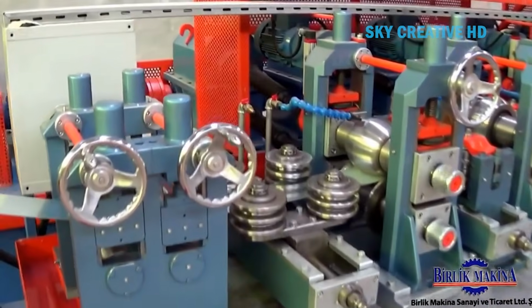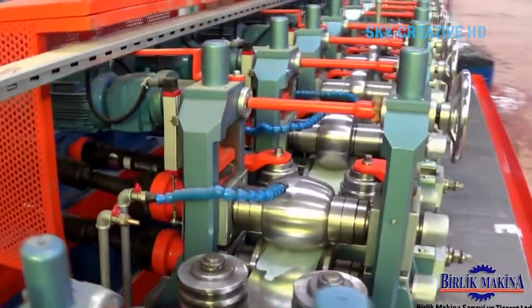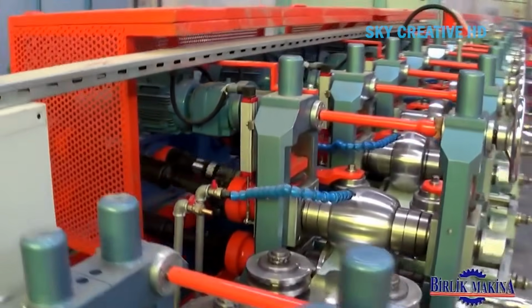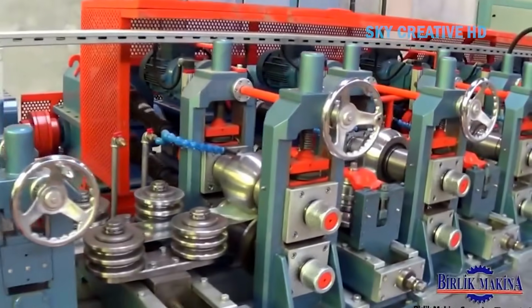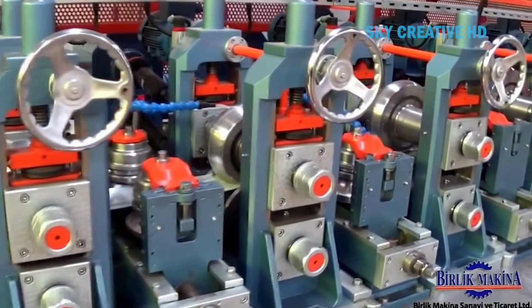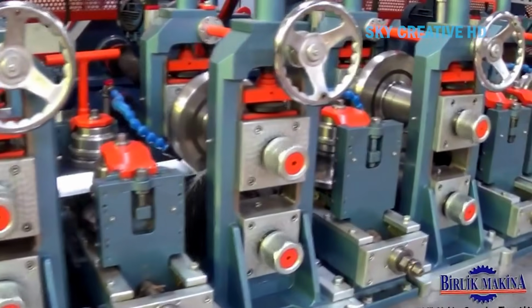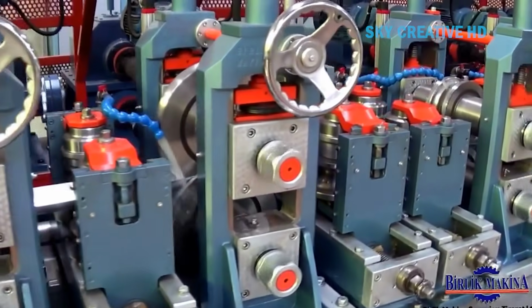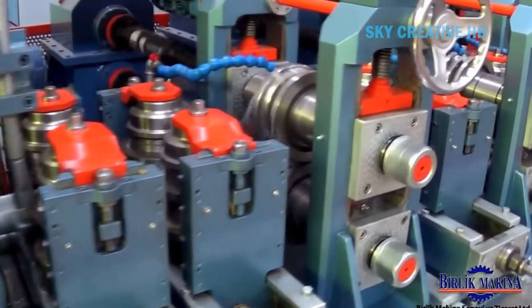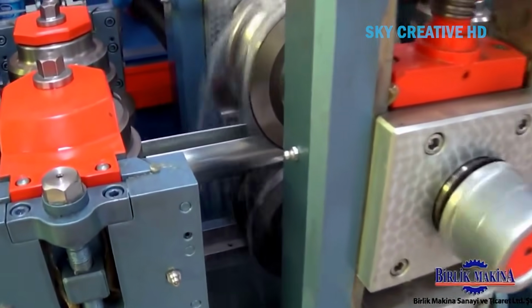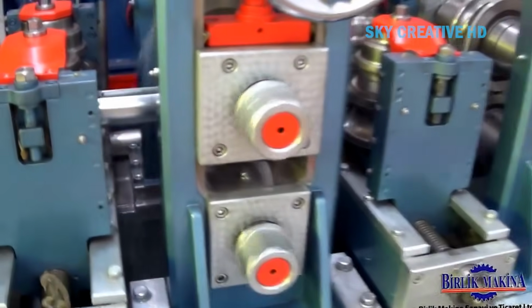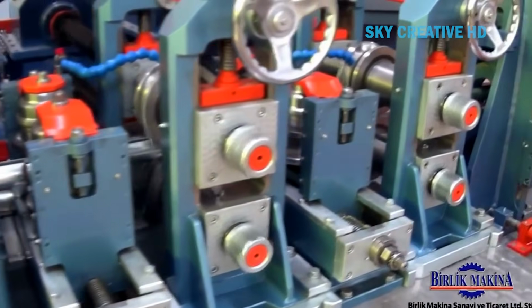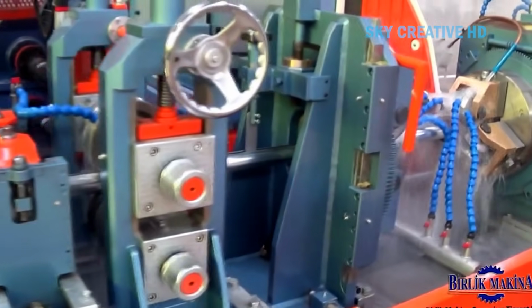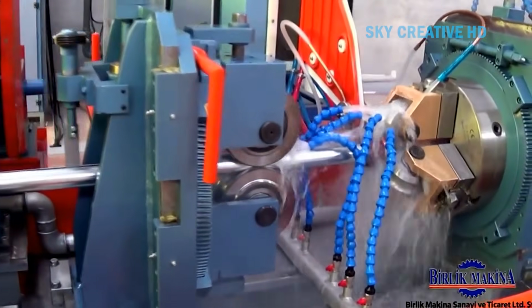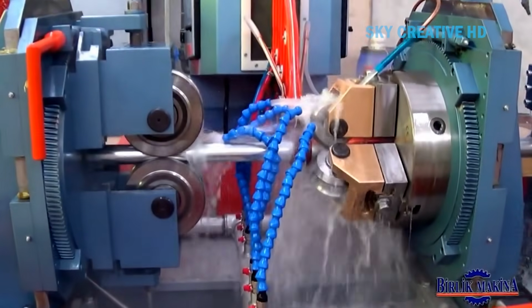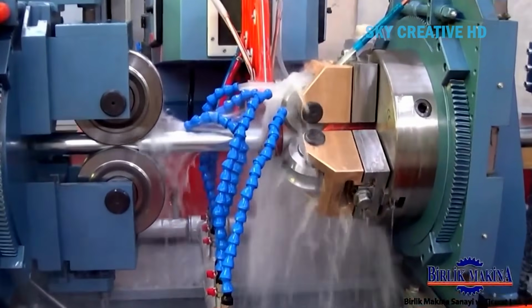ERW stands for electric resistance welding, and the name pretty much tells the story. A flat strip of steel, called a skelp, is fed into the line from a large coil. As it travels through the mill, a series of forming rolls progressively bend it from a flat strip into a tubular shape. By the time it reaches the welding station, the two edges of the strip are pressing against each other under high pressure, and a powerful electrical current is passed through the contact zone. The resistance of the metal to that current generates intense localized heat, enough to fuse the two edges together in a solid, continuous weld seam. No filler metal, no flux, just heat and pressure creating a metallurgical bond.